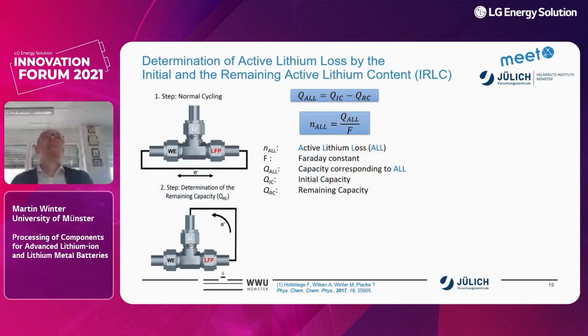So what we did is we actually developed a method for this. We call this the IRLC method, which is a determination of the active lithium loss, ALL, by the initial and the remaining active lithium content, by the differentiation of the two. And what we are doing is a two-step process in a 3-electrode cell with a working electrode, which is, for example, graphite or a silicon-based material. Then we have a counter electrode, which is a cathode material, which should be mostly unaffected by any reaction with the electrolyte. We took here LFP because of the favorable potential. There is not much electrolyte oxidation at LFP, probably nothing. And also we have a lithium-metal reference electrode. In the first step, we are cycling the capacity of the cell between the anode and the cathode.